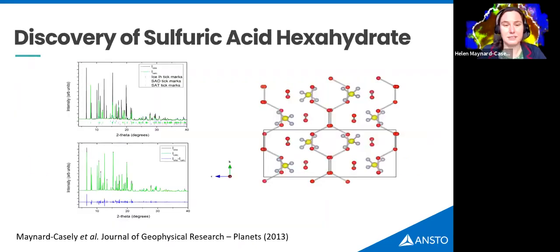One of the things that started this was actually reading that sulfuric acid octahydrate, which was meant to be one of the most dominant materials and still is, a recent reanalysis of the Galileo NIMS data again suggested that sulfuric acid octahydrate will be a major material on the surface. But when I actually looked at the literature back in 2011 when I started this, there were papers that suggested that sulfuric acid octahydrate didn't actually exist, which was slightly surprising.